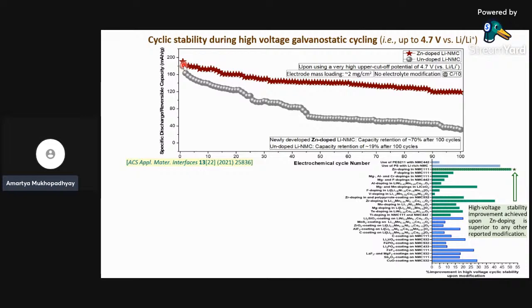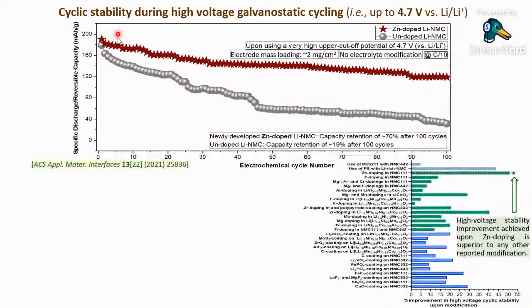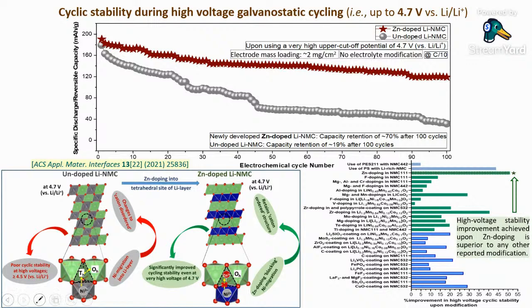So what one can see is with the undoped material, the capacity fade was much more significant as compared to the zinc doped material. Zinc doped material was more stable as compared to the undoped material, and so from an electrochemical perspective, this is the evidence that yes, upon zinc doping, the electrochemical cyclic stability improved in significant terms. And the reason was this, as I had shown earlier, the zinc occupied the tetrahedral site of the lithium layer and suppressed the nickel migration from the transition metal layer to the lithium layer when lithium was taken out from the structure.